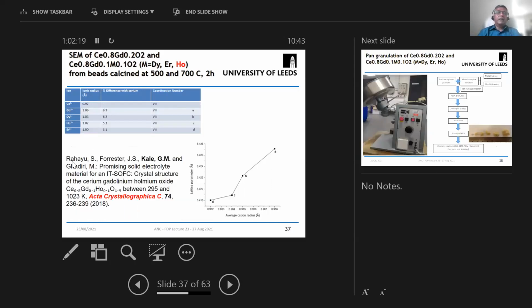So we published part of this work. The holmium co-doped material was published in 2018 in Acta Crystallographica C, where we looked at the change in lattice parameter as a function of average cation radius, and it almost follows Vegard's law, except for point C here, which we don't know why it has deviated from Vegard's law. It could be a negative deviation from Vegard's law, so this still needs to be investigated. We are still looking into that.